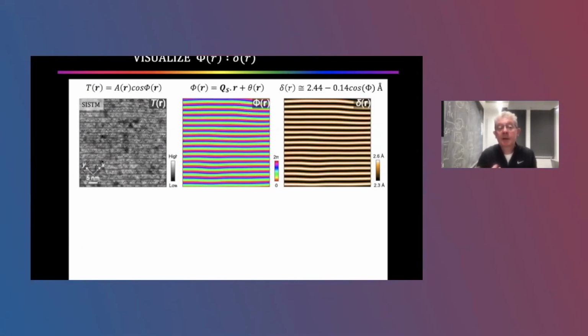Top left-hand side is a topographic image with a tungsten tip. We can see the supermodulation throughout the image. We can measure the phase of the supermodulation everywhere in that field of view. And from the X-ray refinement, we can estimate the apical distance everywhere in that field of view. And the apical distance is changing by more than 0.3 angstroms in that image on the left. So that's with a conventional tip.